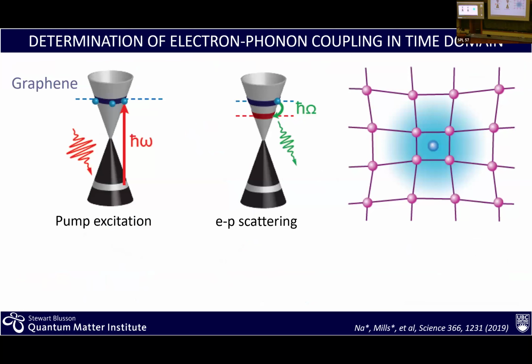Now, as an example of what can be done, just very, very simple, you can do things like looking at graphene. You come in with a pulse that excites an electron from the lower part of a Dirac cone to the upper part, and then you can watch this electron relax. They can relax through electron-electron scattering coming down this cone, but they can also interact with the lattice. And electron-phonon scattering is a critical parameter, determines the performance of electronics, determines superconductivity in some cases. So really it is a quantity of interest, but it's really hard to get as a number.